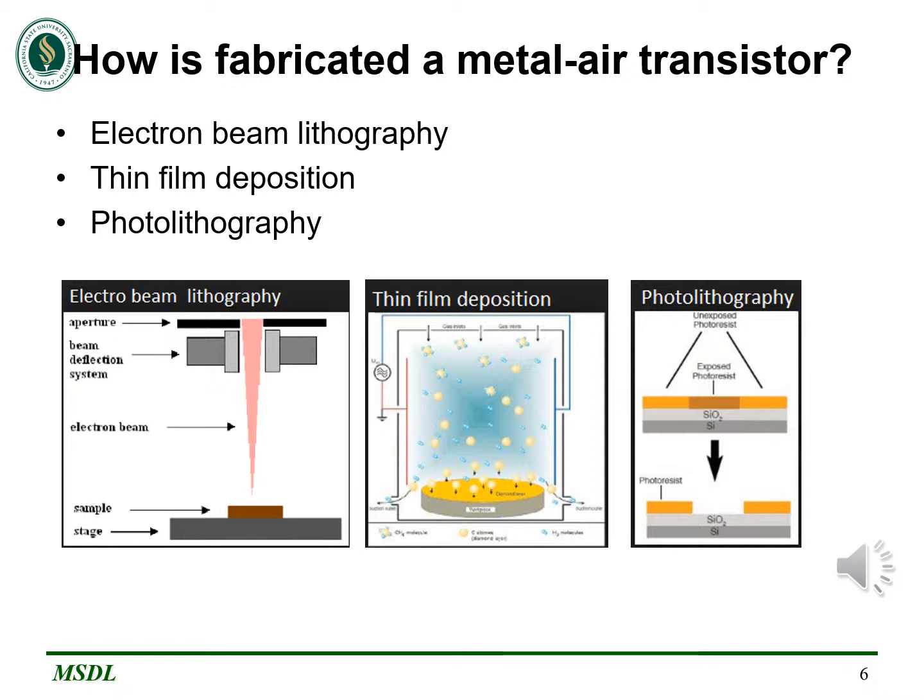Both thin films were deposited sequentially by electron beam evaporation at high vacuum in a Kurt J. Lesker PVD-75 electron beam evaporation system. Metal lift-off was performed in a hot acetone bath at 60 degrees Celsius with ultrasonication. Finally, photolithography was performed to create larger contact pads on the nanoscale devices.